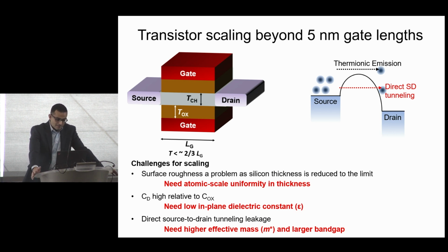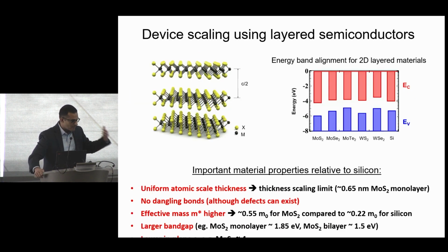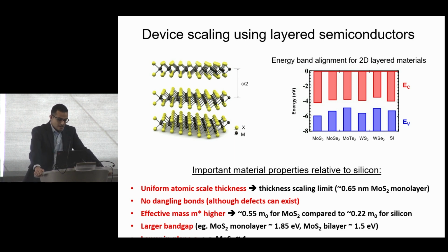And so to overcome these problems, if you want to push beyond 5 nanometer, first of all, you need a semiconductor that is super thin, just from an electrostatics point of view. And it has to be atomically thin with no roughness. You need to have a low in-plane dielectric constant for the semiconductor, lower than what we have in silicon, to reduce, again, the effect of drain controlling the source potential. And finally, ideally, we need to have higher effective mass and larger band gap for our semiconductor compared to silicon. So we need a new material if we want to think about beyond 5 nanometer gate lengths. And I think that's perhaps where, a lot of us believe, 2D materials can come into play.